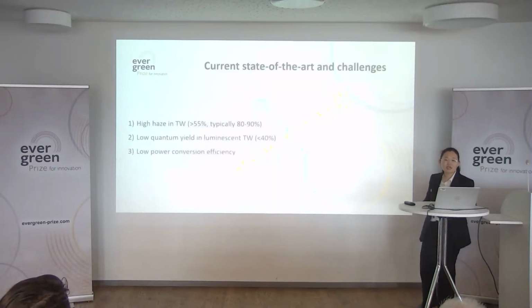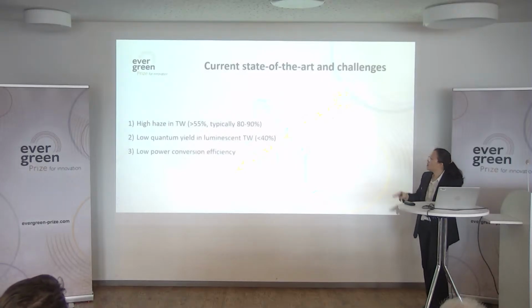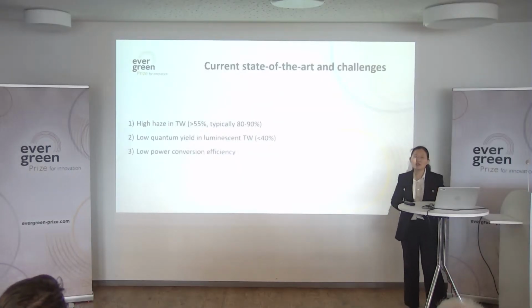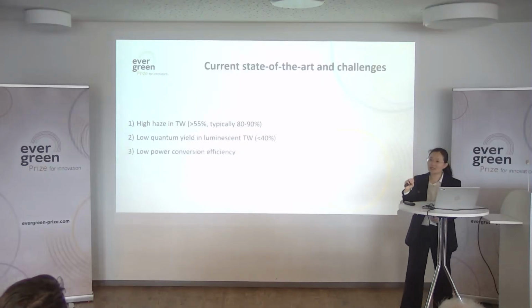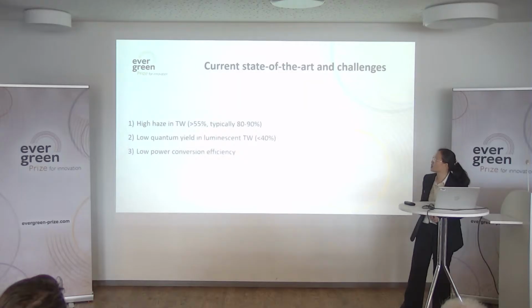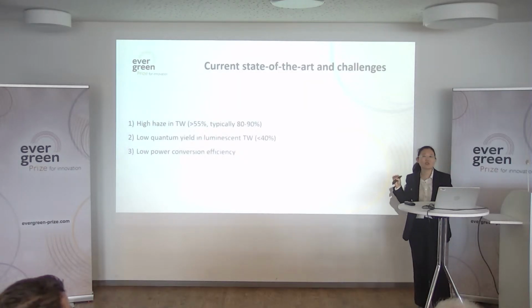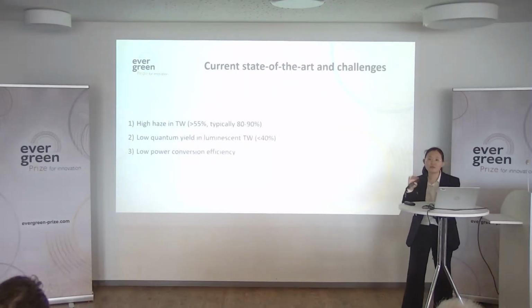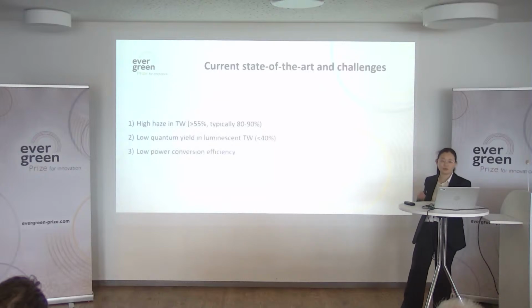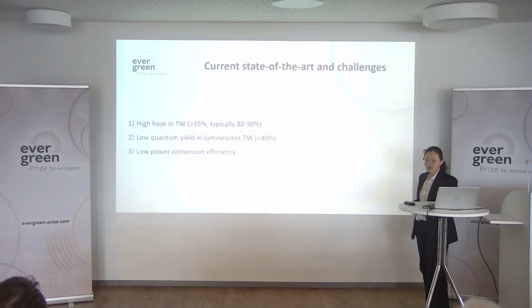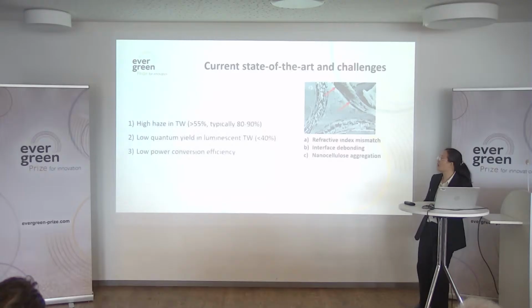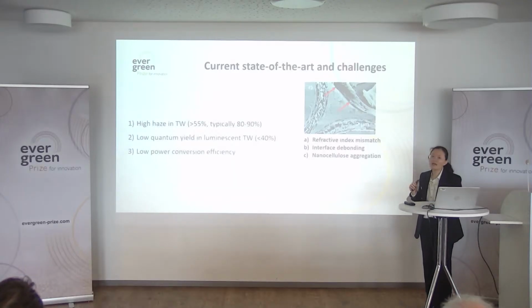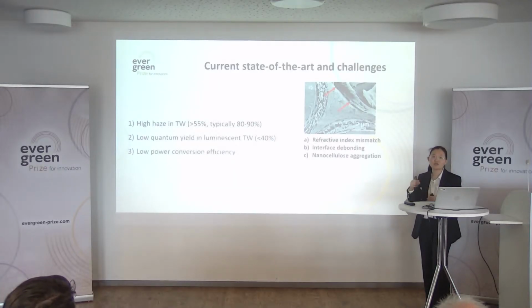So this is the current state of the art. First, the transparent wood currently has high haze, typically 80 to 90%, and we could achieve around 55% now. But for this luminescent solar concentrator device, we need to decrease it further. This is a radical change from the field of transparent wood, and we need a fundamental understanding of the light interaction with transparent wood.